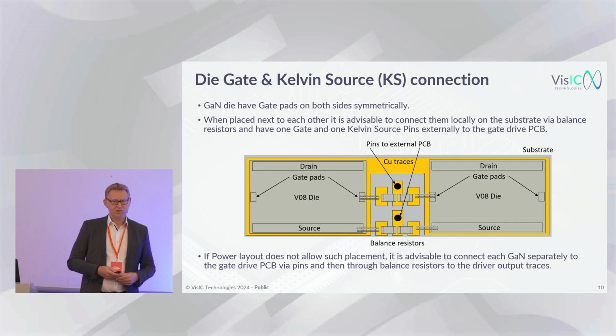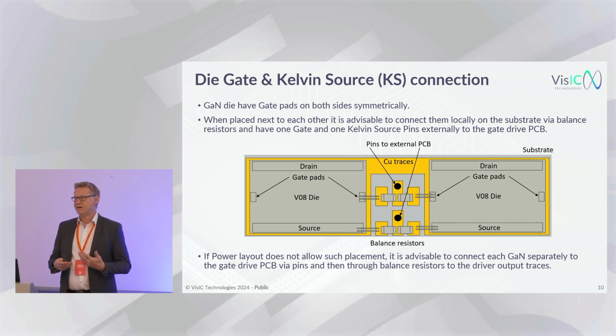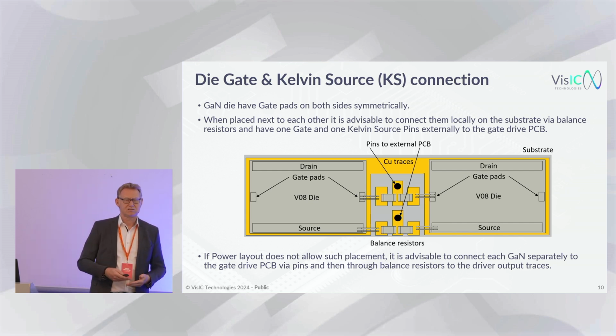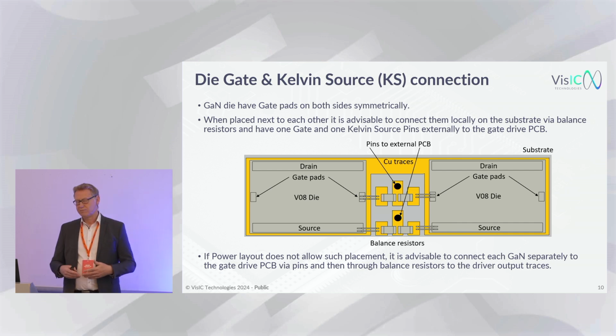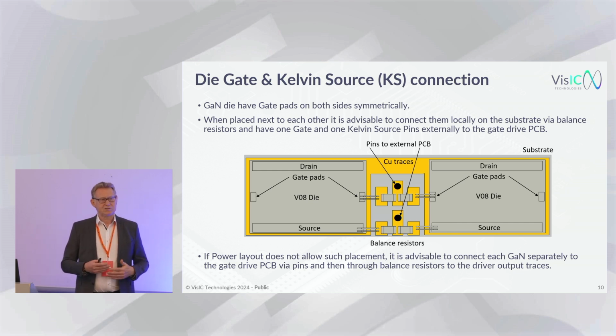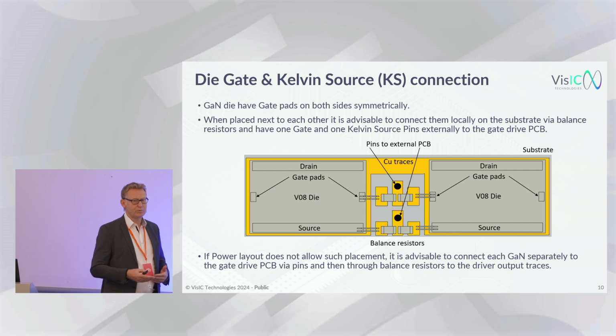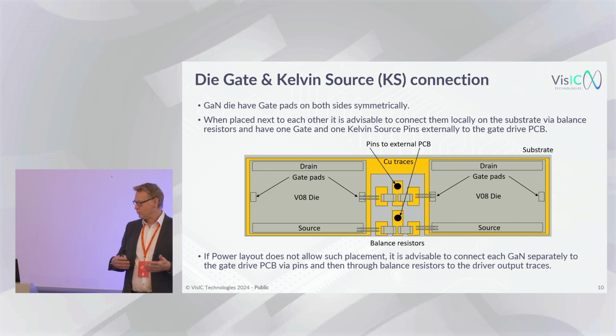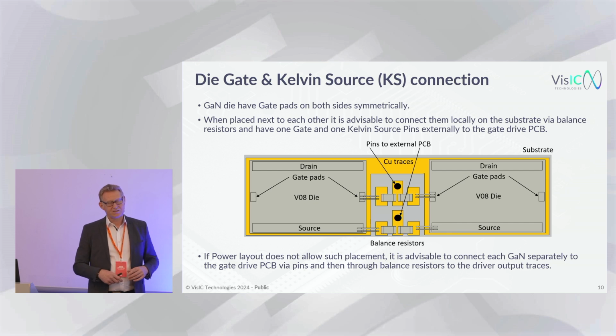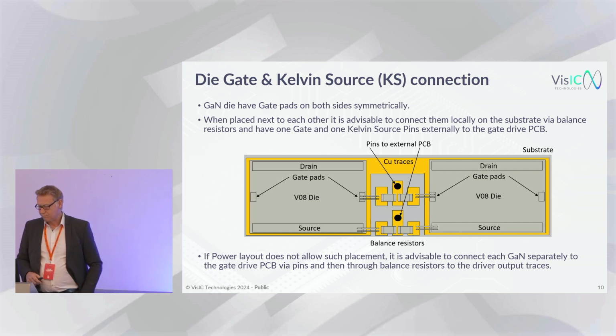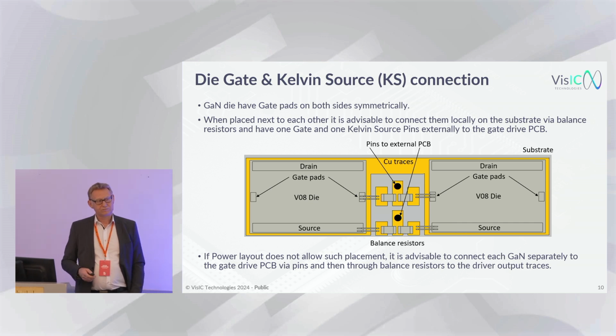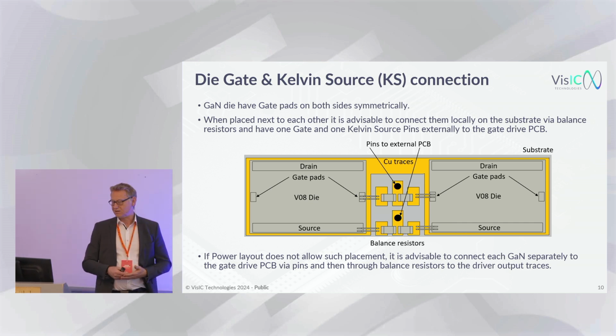Paralleling of devices is an issue, and basically you should follow best practice like you do with silicon carbide or other fast switching devices. So you need balancing gate resistors, which are either discrete mounted, depending on your layout. This is just one example where you can reduce the inductance, especially the gate loop inductance. Therefore, we are mounting two pins here in order to reduce the Kelvin and the gate inductance of the pins, and to facilitate that you can switch the device really fast.